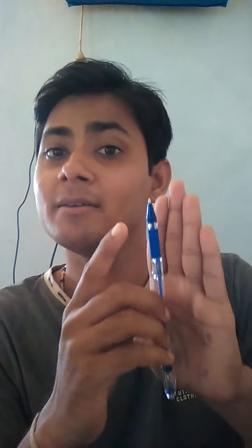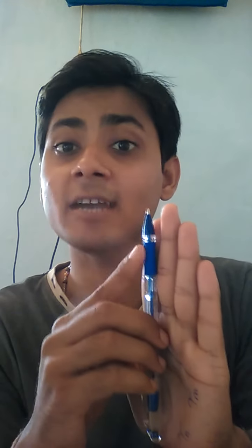So it is blocked here. At the beginning we can catch it, because at that particular measurement time there is not sufficient time to flip the magnetic moment. So at the beginning we catch the magnetic moment at a particular time, which is less than the Néel relaxation time. So here the magnetization is a non-zero value, meaning we get some little amount, but it is not exactly 0 because we are blocked here. At that point it is called the blocked state of the magnetic nanoparticle.